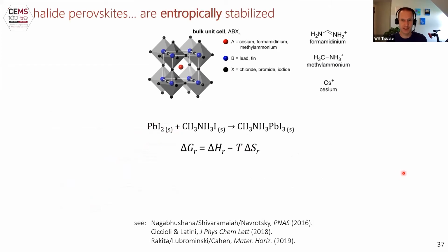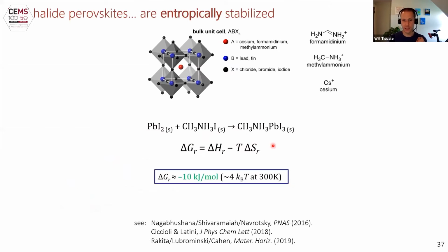Well, the thermodynamics of these materials are even more curious. If you do the calorimetry, you do the experiments, you write down the formation reaction. This is methylammonium lead iodide, the formation from the solid binary lead iodide and methylammonium iodide. You'll see that the free energy of formation is negative, as it should be for a stable crystal. Only it's slightly negative, only a few times kT at room temperature. But remarkably, the delta H of formation, the enthalpy of formation, is actually positive, which is telling you that it's entropy that is stabilizing the crystal, that this is a crystal really unlike other inorganic semiconductors that we've experienced, where the strength of the material is determined by the bonds. In this case, the strength of the material is really determined by the entropy of the overall crystal.